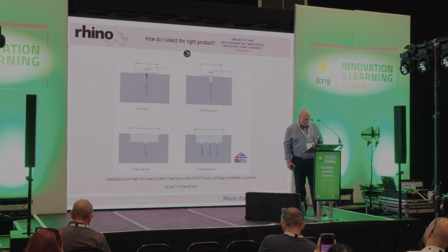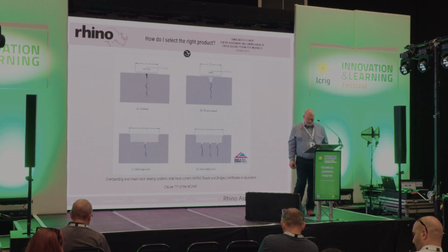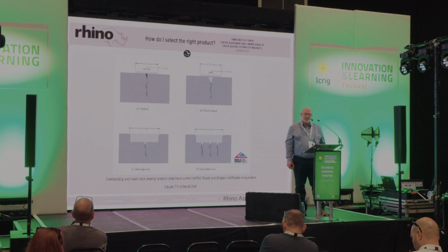In 2010, the BBA formed a specialist group to understand how to specify the repair of cracks, and how this could be specified and certified. In the top left of your image there, you'll see simple overbanding, and this is for single cracks of up to 5 millimeters wide, which can then be treated with a simple overband repair of up to 40 millimeters wide. The top right image shows a fill and overband treatment, and this is for a single crack of up to 40 millimeters wide, with a maximum band repair of 200 millimeters wide.